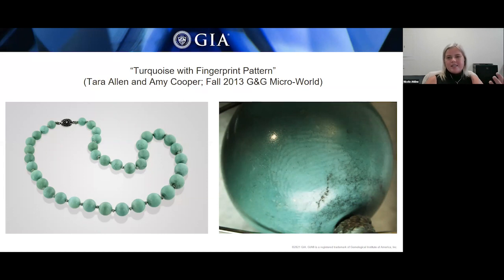So untreated turquoise is porous and often absorbs skin oils and other contaminants. It's thought that the fingerprint pattern could possibly be a result of glue or another impurity present during initial handling, and then wear over time preserved that pattern and made the discoloration of the bead more distinct.